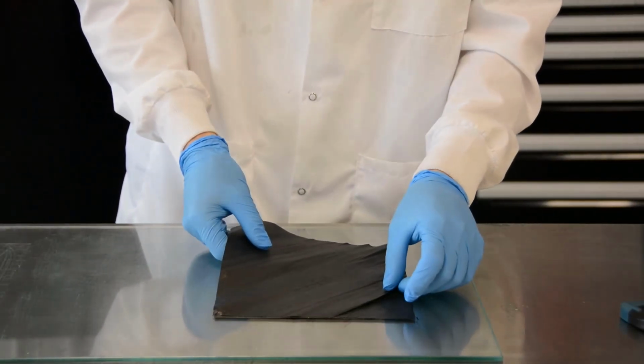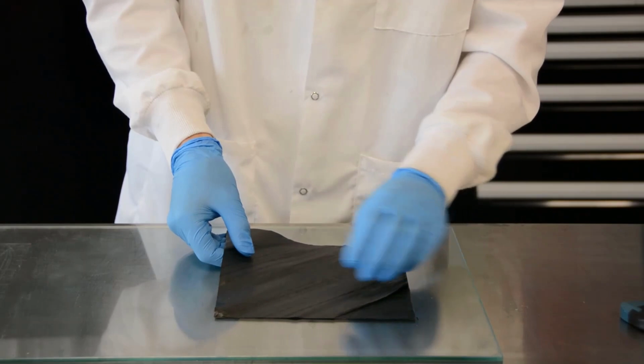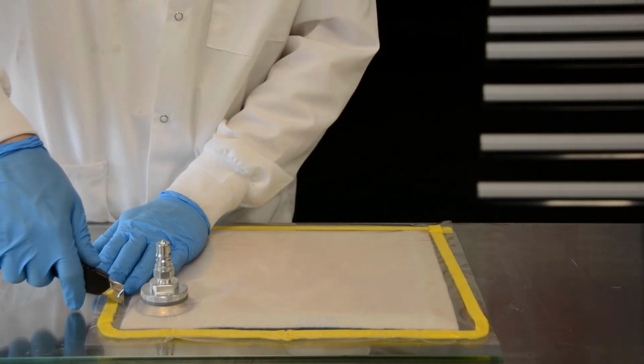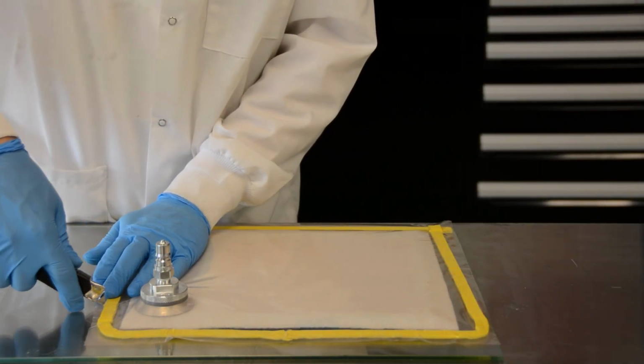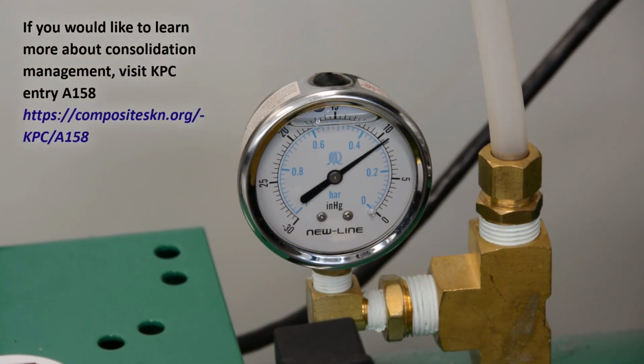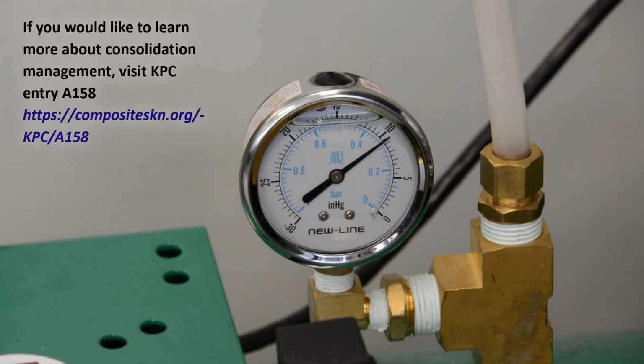We will now prepare an identical panel, but we will not debulk between layers, and we will introduce a leak in the vacuum bag. We can see that the part is not under full consolidation pressure as a result of air flowing into the bag through the leak.